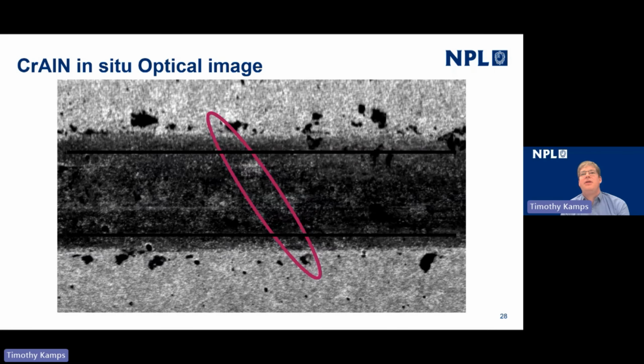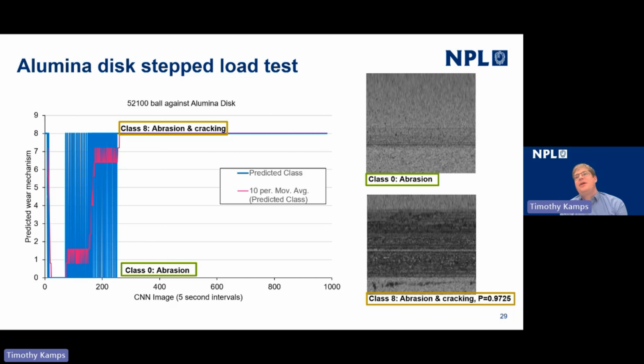An example of the use case for this system is shown on this slide for a ceramic contact. So this is an alumina disc with a 52-100 ball being slid against it. So a bearing steel ball. And what we're looking at here is that in the early parts of the test, we had some mild abrasion occurring on the surface, and this developed into having some cracking.